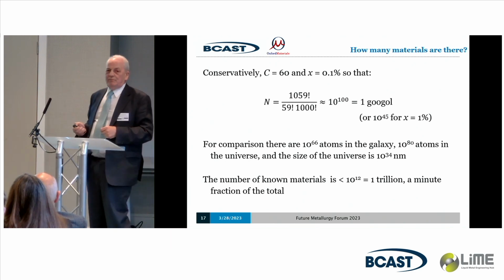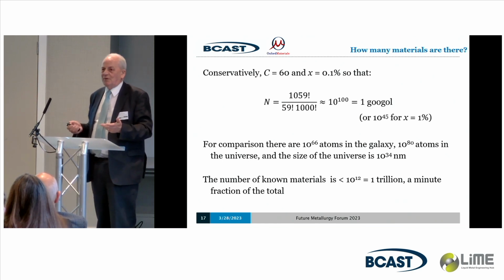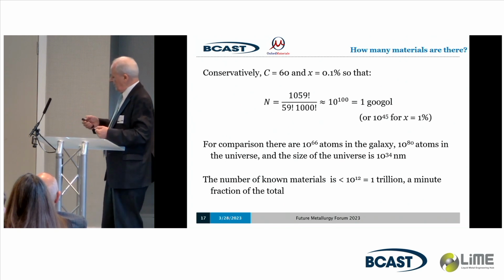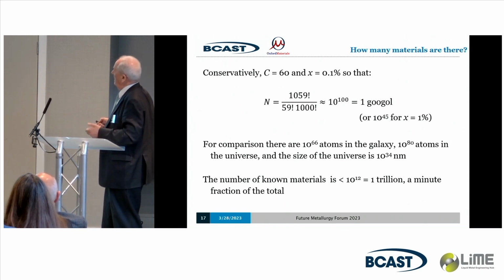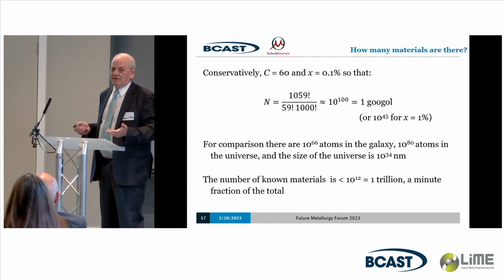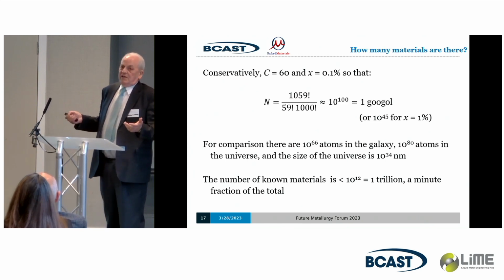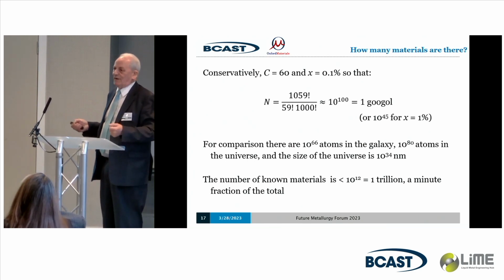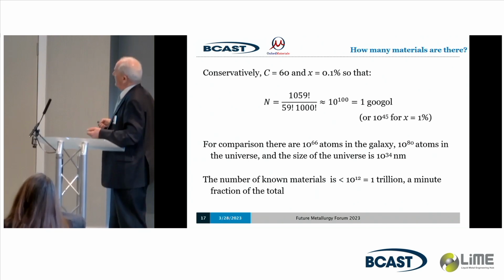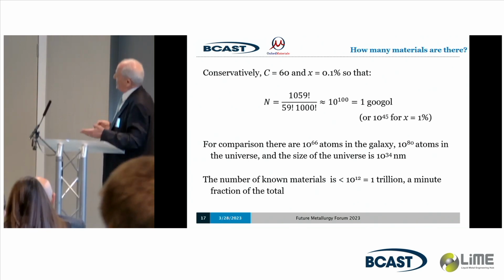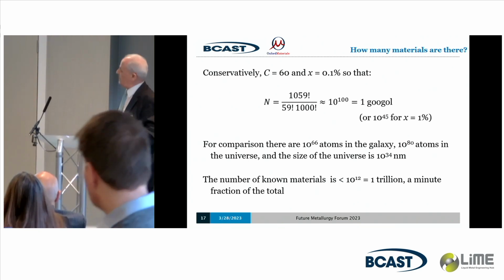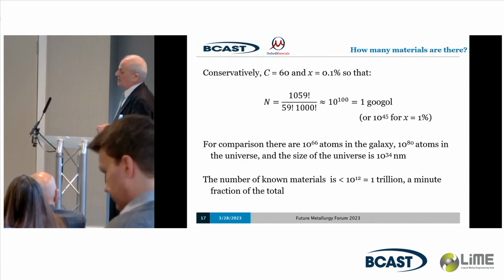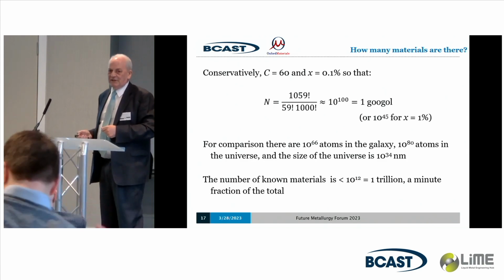What's the specification? Most engineering materials are specified to 0.1%. We know as material scientists, you change the composition by that much, you can change the material properties pretty dramatically. But often, it's specified to 0.01%. The highest strength steels and the best semiconductors are specified sometimes to parts per million. But let's take 0.1%. A reason I take 60 and 0.1%, that's pretty conservative, and it turns out the answer is there's 10 to the 100 different materials.